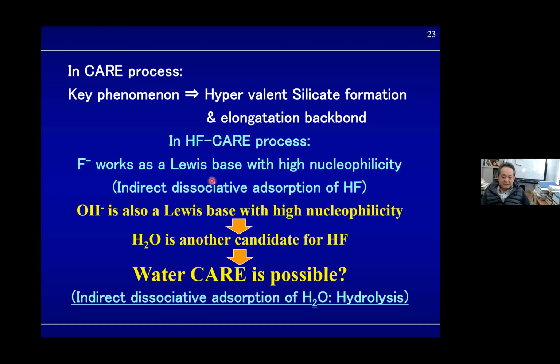In the HF case, the etching mechanism was indirect dissociative adsorption of the HF molecule, but in this case, the mechanism becomes indirect dissociative adsorption of a water molecule, and this has a name, hydrolysis reaction. Okay, so if this becomes possible, the CARE process becomes more environmentally friendly.